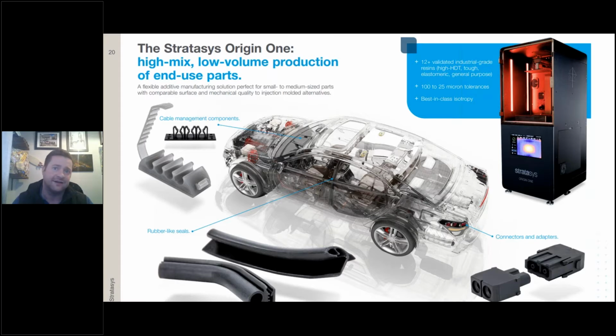Multiple sensors inside the machine monitor what's going on with separation forces, the exothermic reaction from when we project an image and it cures the material, all the way through to the heated build chamber, which is key. So we're able to control the build chamber. Materials like 3955, for example, that need to be maintained at 60 degrees C throughout the build, we can do that, and we can do full build envelope in X, Y, and Z, so solid brick parts if you wanted them, which proves how stable and repeatable the system is.